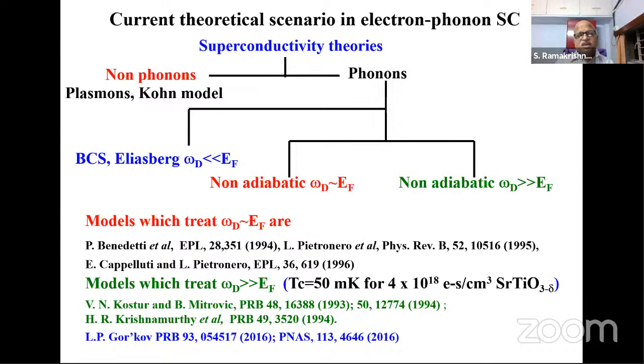The electron-phonon interaction is the hallmark of BCS superconductivity. But there are systems where the phonons won't work, especially in non-adiabatic systems. I told you that the Fermi energy is compared to the lattice energy. This is where the bismuth comes in. There are systems like strontium titanate where the omega D is even larger than EF. So there are some theories proposed for that. And unfortunately, what is developed for strontium titanate doesn't work for bismuth.